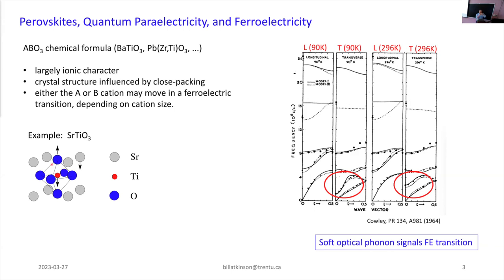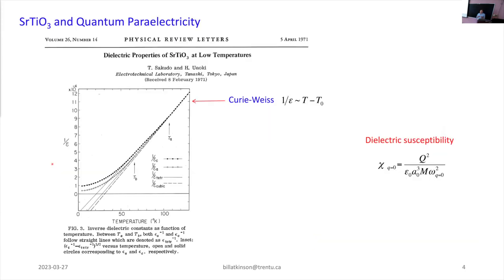So the titanium moves off center, the oxygen moves a little bit off center the other way, the strontium moves off center. And the distances that we're talking about are fractions of an angstrom. These aren't huge distortions of the cell. Now, strontium titanate, I love this paper. This is a paper from 1971. It's a beautiful set of measurements on a single crystal of strontium titanate. Strontium titanate never becomes a ferroelectric.